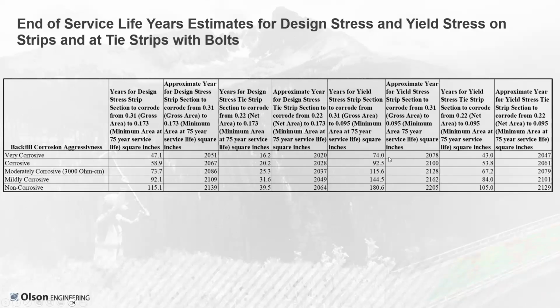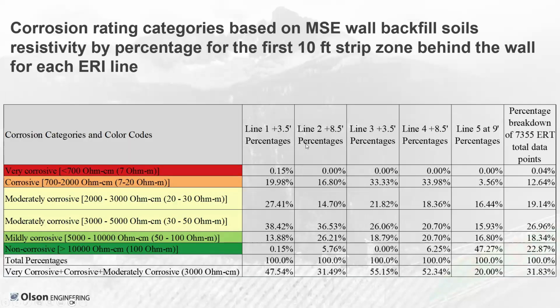Then you can see that even in very corrosive areas, it would have been 74 years and it would have met the service life here at 2078. So it was showing that there was cause for concern, but in the worst case of getting to yield stress, it still should perform over the service life. And those years are predicted there at the right of approximate years to failure as well. Obviously, it's much sooner here with it coming in at 2047 versus 2061.